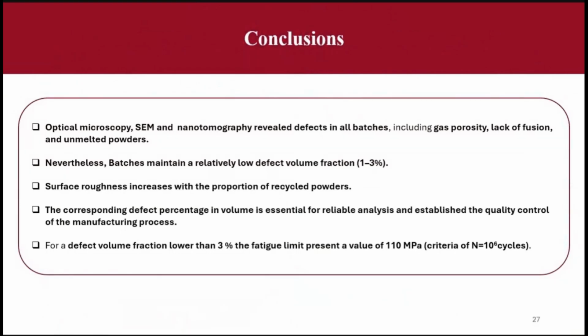As a conclusion, optical microscopy, scanning electron microscopy, and nanotomography must be used all together to characterize the material and reveal defects in all batches, including gas porosity, lack of fusion, and unmelted powders. Nevertheless, the batches maintain a relatively low defect volume fraction, and this is the important point. Surface roughness increased with the proportion of recycled powders, as many authors have concluded also. The corresponding defect percentage in volume is essential for reliable analysis and to establish quality control of the manufacturing process.